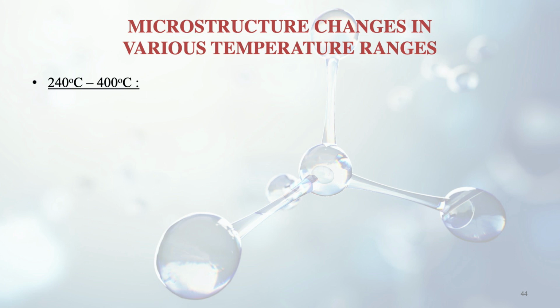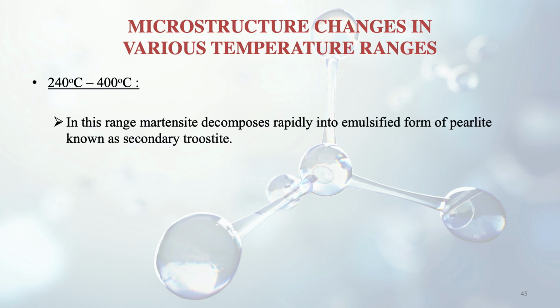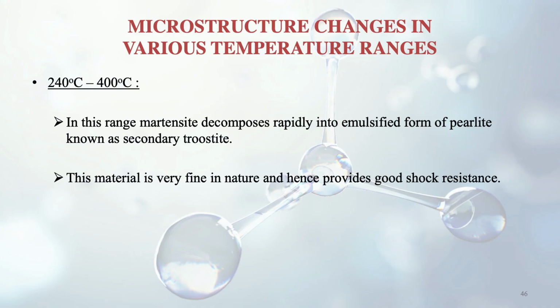In this range, martensite decomposes rapidly into an emulsion-like form of pearlite known as secondary troostite. So pearlite is now formed when we move in this temperature range 240 to 400 degrees centigrade, and it's a rapid process. And this material is very fine in nature. This troostite is very fine and hence it provides good shock resistance.